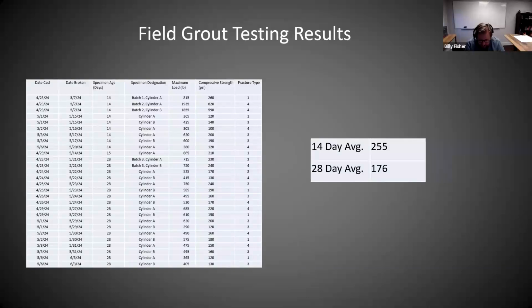Not really sure what led to that ultimately, other than they were very low strength samples - I don't know if that had more to do with the curing of the grout or maybe the handling of it. Some of the samples were damaged because it was difficult to get the sample out of the mold. We actually had to go to the testing lab just to help them with that.